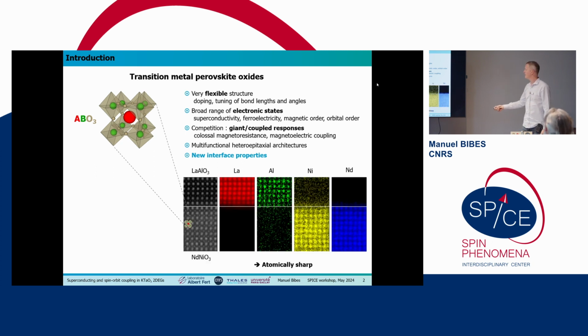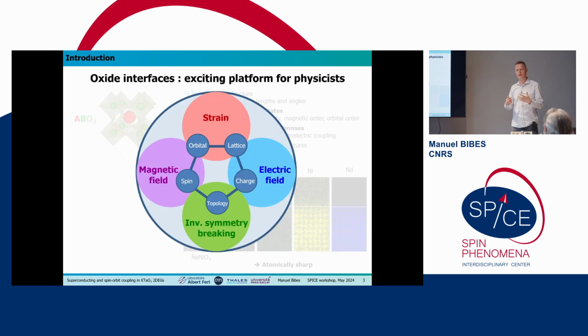And this is just one example. There are, of course, many in the literature, of a quite sharp, actually atomically sharp interface between two compounds. This is a nickelate with metal insulator transition. This is just a conventional insulator. But the possibility to combine these materials into almost perfect heterostructures brings a lot of exciting possibilities. You typically are going to have a reconstruction of the orbital, lattice, charge and spin degrees of freedom at these interfaces. And you may have some topological properties arising from the combination of inversion symmetry breaking and spin-orbit coupling. And of course, then you can play with external stimuli to act upon this new ordered state.